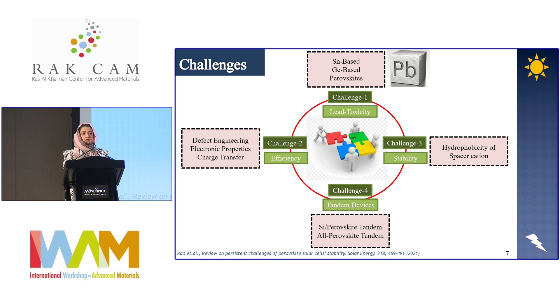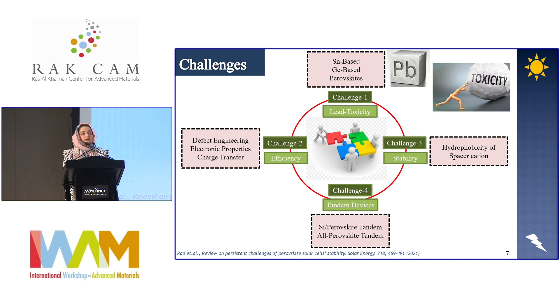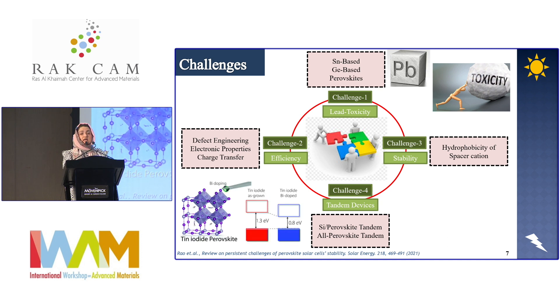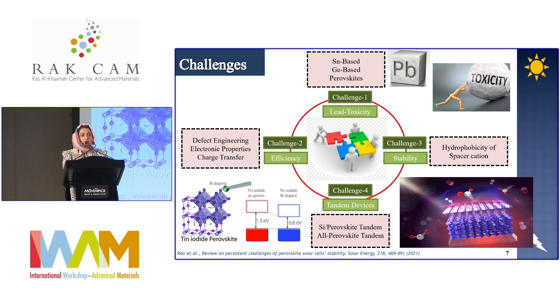There are a few challenges to overcome to bring perovskite solar cells into the commercial world. One is lead toxicity — lead is toxic, so we can replace it with neighboring elements like tin and germanium on the periodic table. This is done using alloying engineering: whenever an element is replaced, new features, new structures, and new electronic properties emerge. Another challenge is stability, which can be overcome by using two-dimensional perovskites, because they have an organic layer that covers the chemically reactive inorganic layer. By combining efficiency and stability through tandem solar cells — layers of different types of perovskites — we can solve all these challenges.